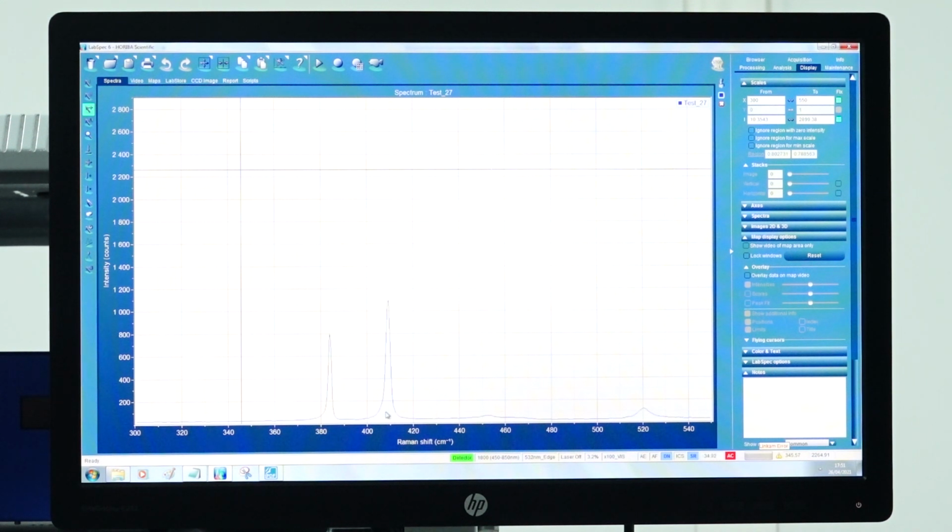These kinds of Raman signatures help us obtain a lot of information about the material that is present. Had it been at 403, we would say that it is a monolayer of MoS2, but it is shifted, and this denotes that it is a multilayer MoS2. And we had also observed the same in the microscope image. You can also see that there is a small peak at 520.7 centimeter inverse. This belongs to the silicon peak, and it is very attenuated because it was a bulk material on which the laser was shined.